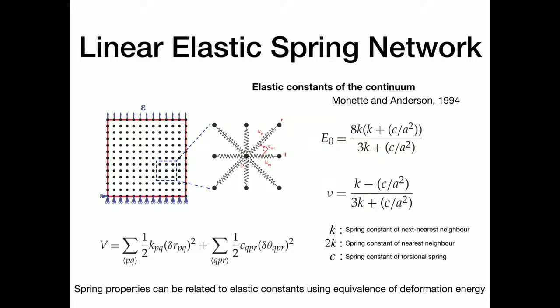And so the energy can be written in terms of the deformation of the lattice, and this energy is compared with the strain energy of the continuum to establish the connection between the continuum properties, elastic modulus and Poisson's ratio, with the extensional springs, torsional springs, and the lattice parameter. So this allows us to connect to experimental data in terms of not only the fracture characteristics like avalanche statistics, but also force deflection curves and prediction of even loads at which failure will occur, kind of.